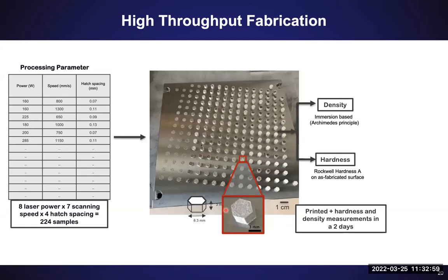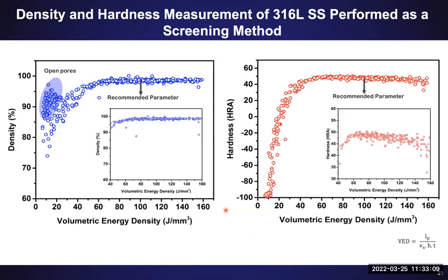The cool thing about this process is you can print the materials and do these density and hardness measurements within 2 days, which is pretty fast. Once we have those materials, here's some data. We were looking at 316 stainless steel as a kind of model material that we were studying with Wisconsin. Wisconsin printed more than 200 samples, and then they basically are measuring the density and hardness.